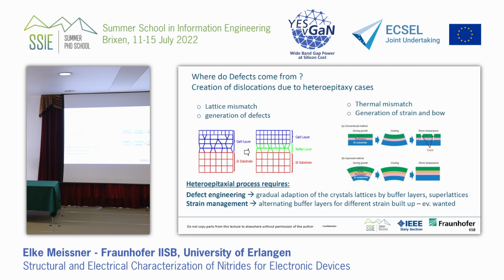So this is to remind you what happens if we do epitaxy. We do heteroepitaxy now, the heteroepitaxy case. We gradually adapt the lattice, and because it consumes energy also, we have to make an energetical step forward to adapt two lattices that initially don't want to be together. So it consumes energy and it creates defects. We can mitigate this by putting in buffer layers. This is actually what we do, from an energetic point of view, in heteroepitaxy.